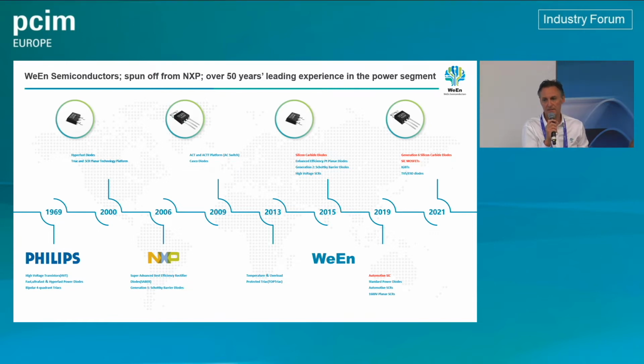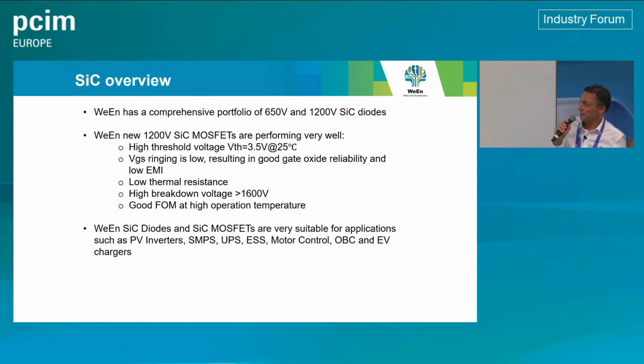So a low VF means that you not only have the very fast switching performance, but also you have low VF and thus lower conduction losses. And very important, last year we introduced our first silicon carbide Mosfets at 1200 volts. So about our diodes, as I said, we have 650 and 1200 volt silicon carbide diodes. They're made in MPS technology, and we use wafer thinning when the product is ready.